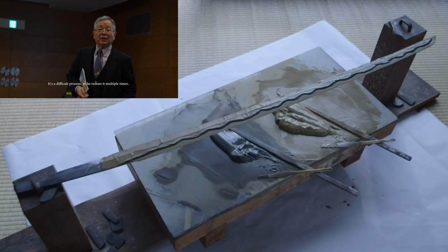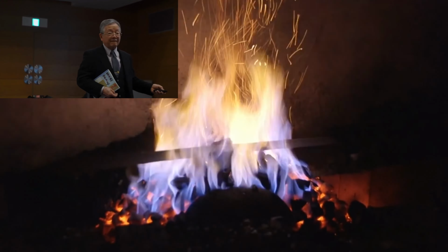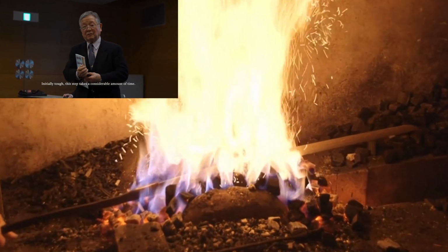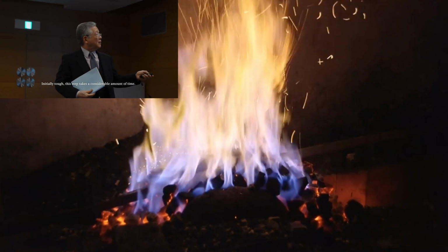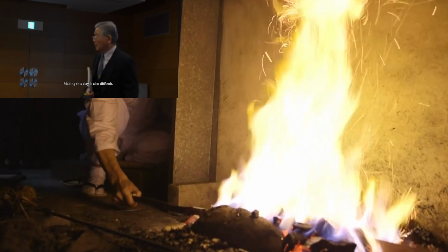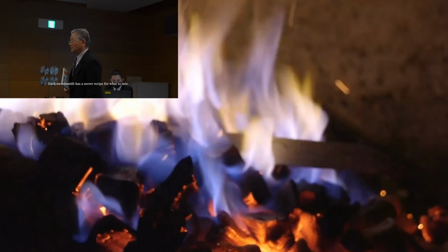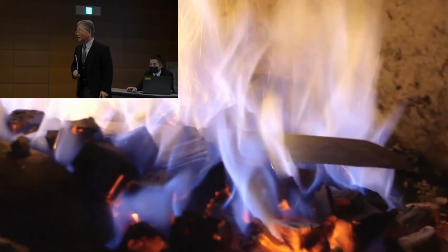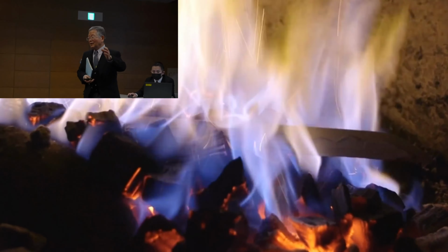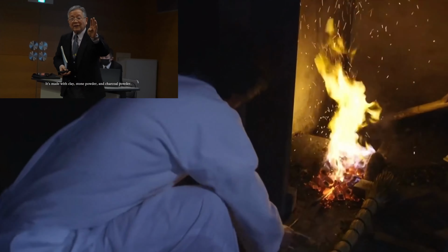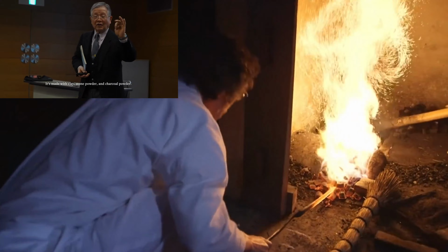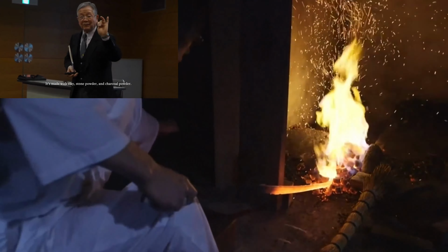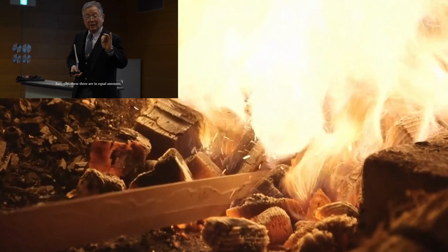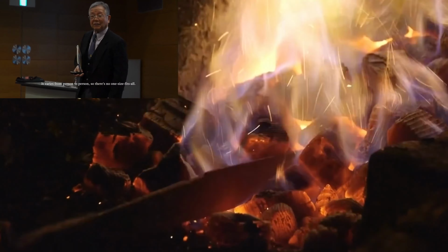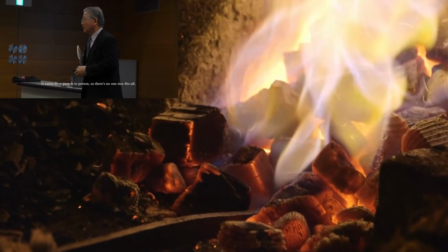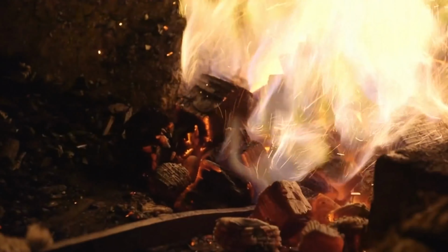One of the key factors in Japanese bladesmithing is the selective hardening, also known as differential hardening. The hamon outlines the transition between the region of hardened martensite steel at the blade's edge and the softer perlitic steel at the center and back of the sword. This difference in hardness is the objective of the process. The hamon itself is purely a side effect. However, the aesthetic qualities of the hamon are quite valuable, not only as proof of the differential hardening treatment, but also in its artistic value, and the patterns can be quite complex.